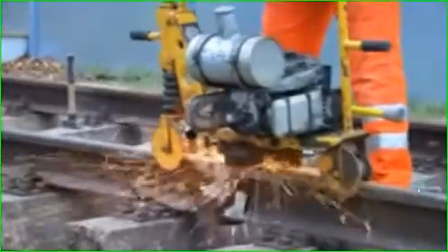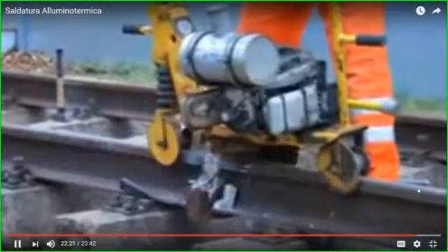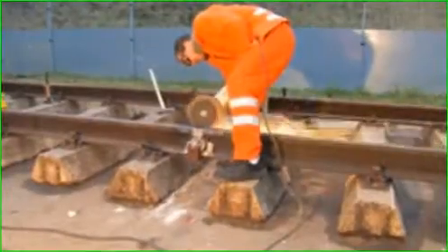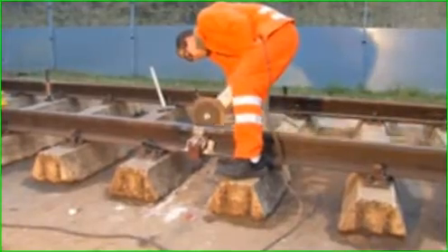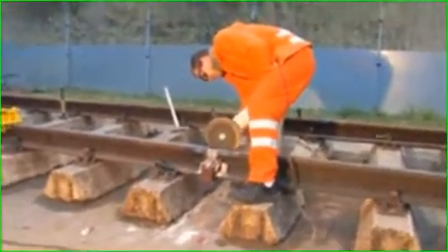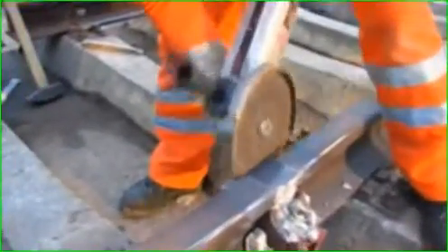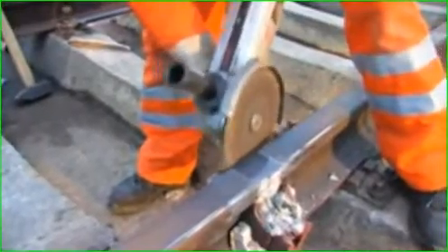The residual welding material on the running surface and on the running flank will be ground off. The shrinkage downwards is finished not before the ambient temperature is reached. Therefore, a small oversize has to remain after rough grinding. In case of reassembled and tightened fasteners, the weld could now be passed by a running wheel.